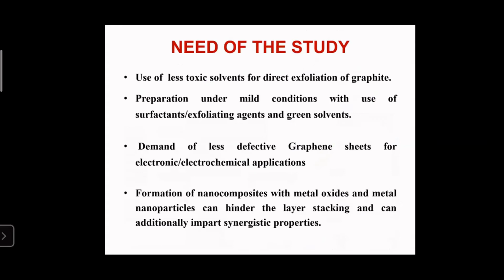But here, by using ethyl cellulose, in addition to exfoliation of graphite, ethyl cellulose additionally leads to edge functionalization of graphene. These functionalities can help in the incorporation of metal oxides. So here we prefer the use of less toxic solvents for direct exfoliation of graphite, and we prefer preparation under mild conditions with the use of surfactants or exfoliating agents. Our exfoliating agent is ethyl cellulose, and we prefer green solvents. We use isopropyl alcohol for the exfoliation of graphite. Ethanol can also be used successfully.